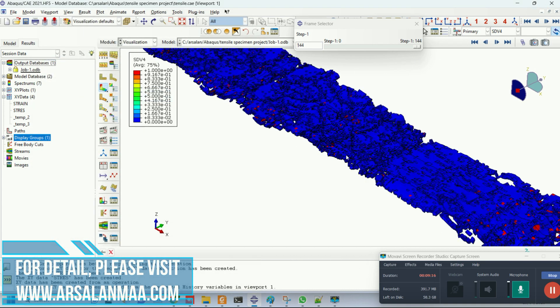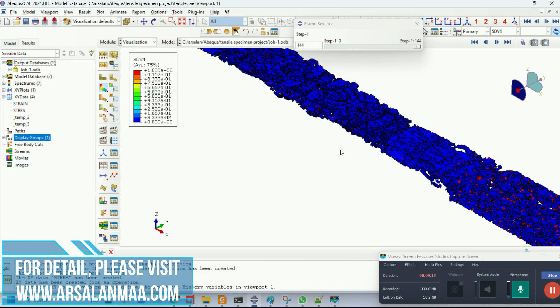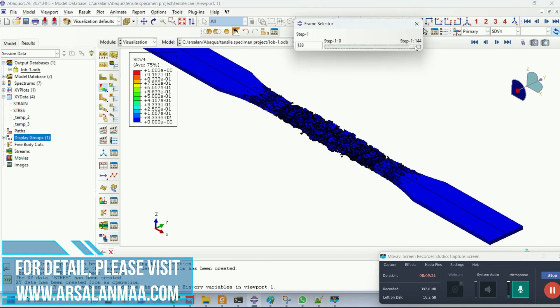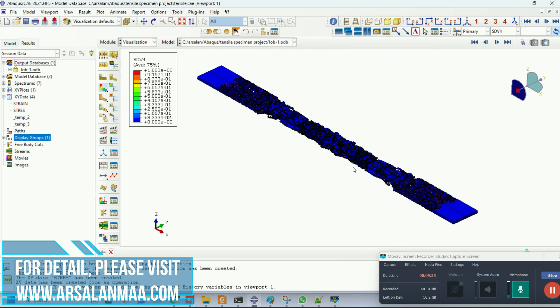For the 90° orientation, the 90° layer is also damaged, but the extent of damage is much less compared to the 0° orientation. We can conclude that if you want to add a composite inside the aluminum, the layer orientation for such a case should be kept at 90°, as the damage instance is less for 90° compared to 0°.